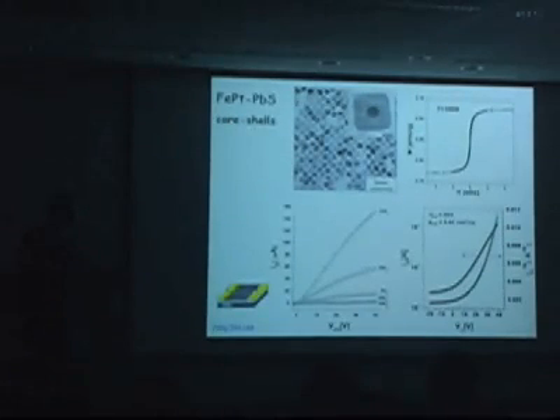This array of particles is superparamagnetic at room temperature and ferromagnetic at low temperature. And at the same time, we can control currents through these arrays by using an electric field. So we can make transistors out of them and get pretty decent field effect mobilities in such arrays. So it's both a magnetic and semiconducting system at the same time.